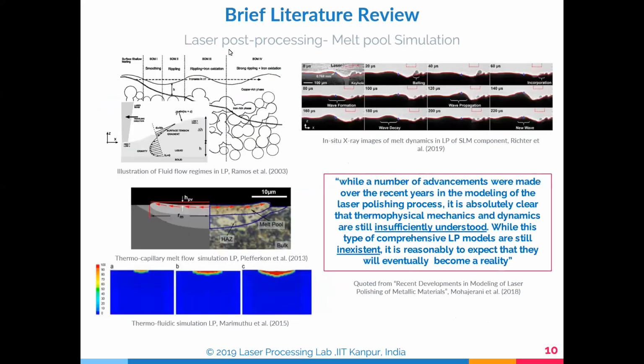Now, looking at this microscopically, we get the melt pool simulation. Basically, when the laser hits and is also moving, a gradient is formed. Because of this gradient, a surface tension gradient occurs. This surface tension gradient will either suck the melt inside or pull it out, depending on the situation. If the gradient is there and the suction is pulling outside, you will always have a dent in the surface. These are wave decay, new decay, small incorporation, and balling. These are keyhole defects, which happen because of melt vaporization. When we do the thermocapillary melt flow simulation, we see how the laser hits the workpiece surface, how it melts, and how it moves.